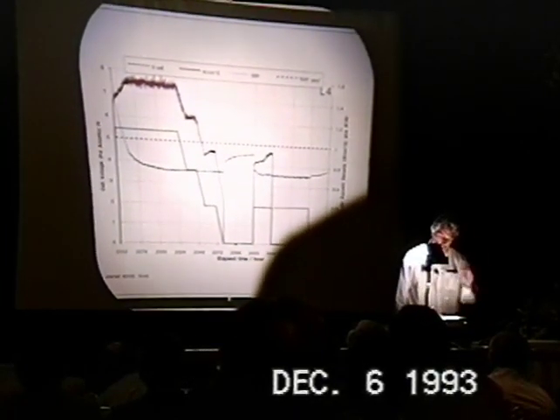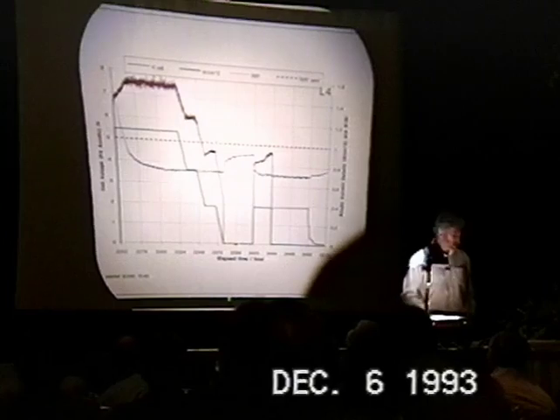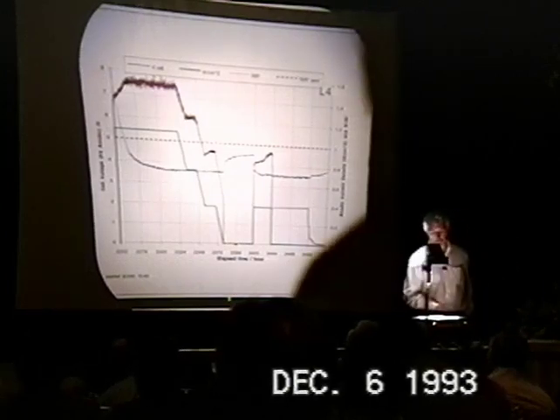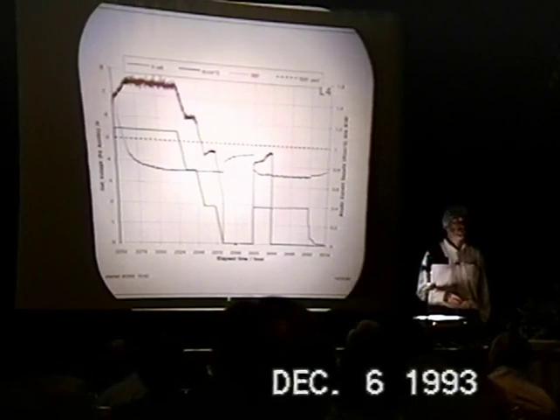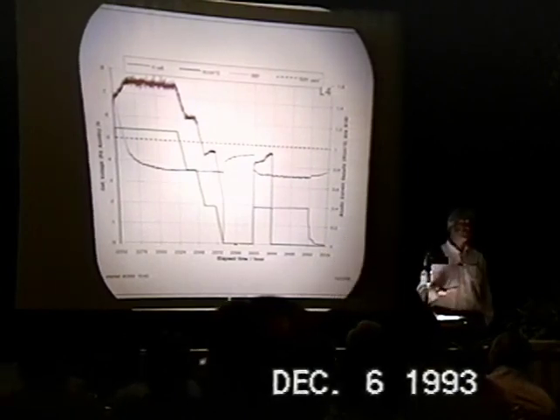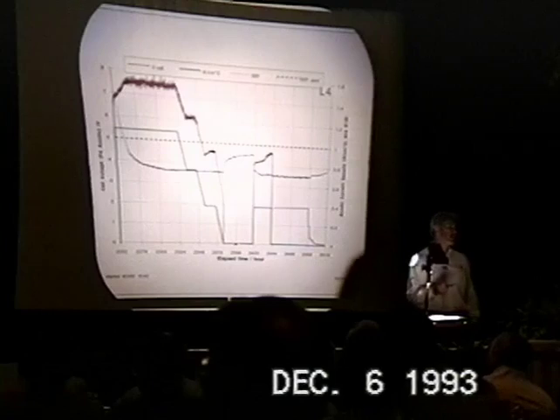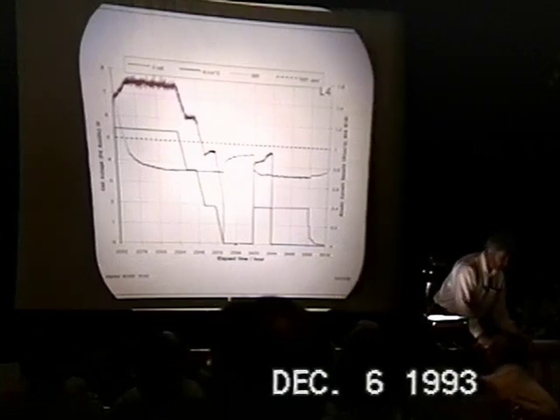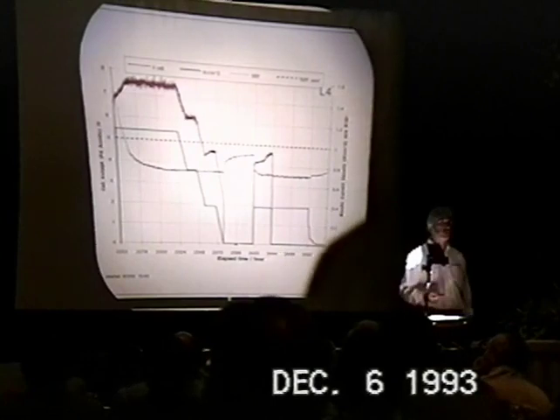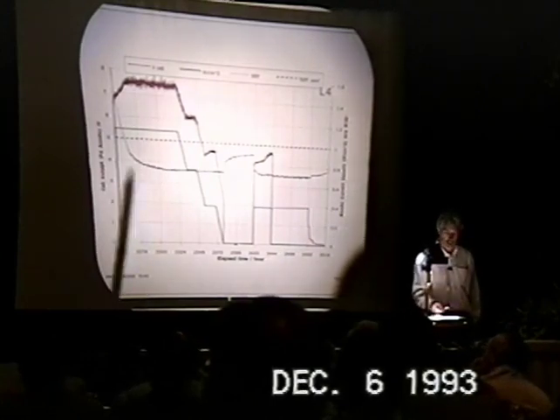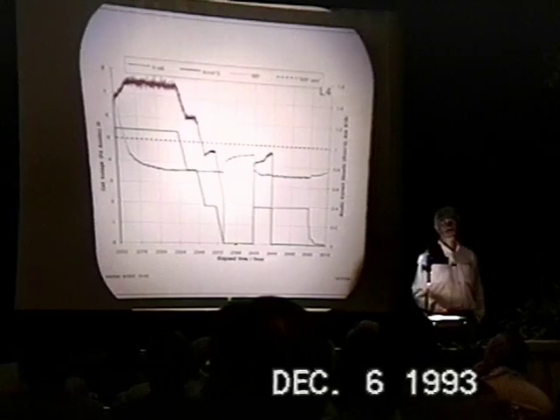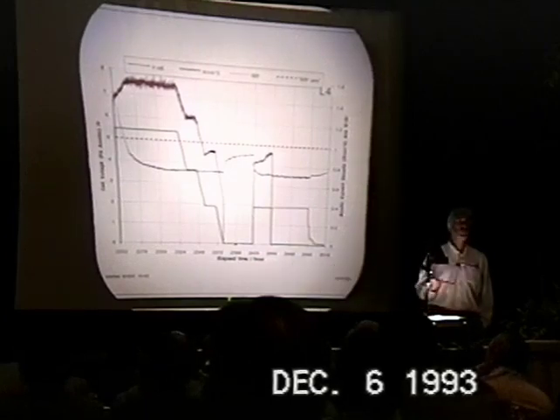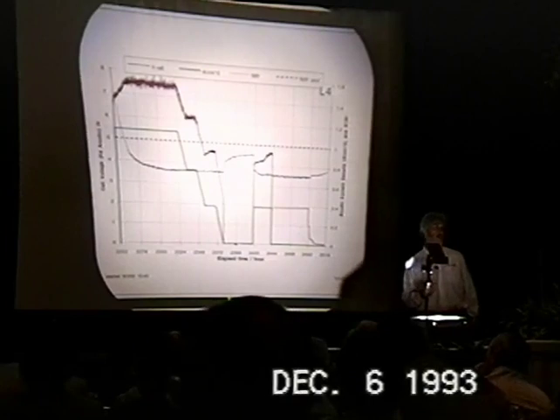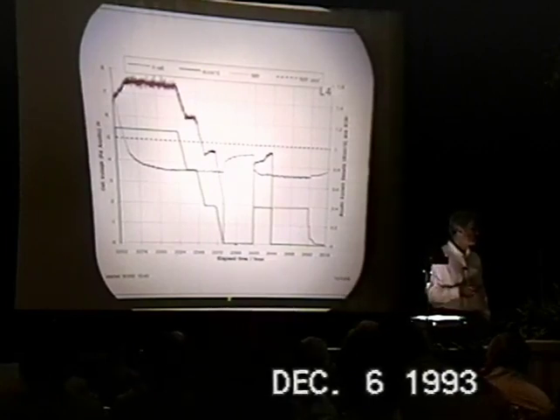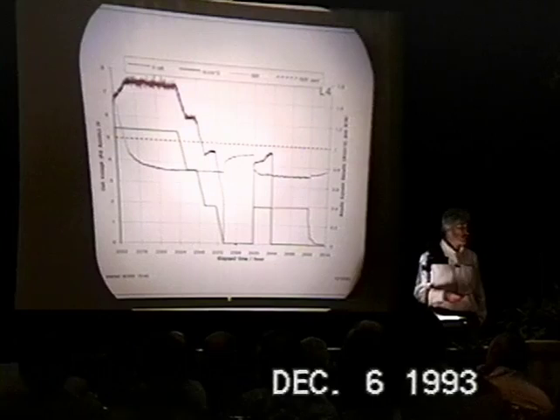Final point, and I will stop. The loss of resistance business, which I present as more of a mystery than a contribution to your understanding. At the end of the experiment, we typically strip all of the hydrogen out just to facilitate the post-test analysis, so that you don't have the hydrogen molecular ion contributions to the SIMS analyses. We always find the resistance at the end, after we've stripped all the hydrogen out, is within 1% of the resistance of the cathode at the beginning, unless something untoward has happened, such as cracking.